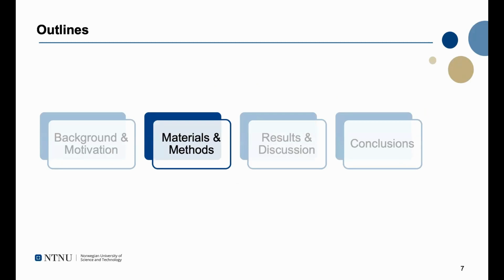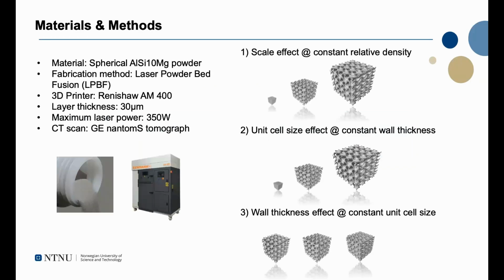So let's jump to the materials and methods. All the specimens are fabricated from aluminum silicon magnesium powder with laser powder bed fusion. The layer thickness is 30 microns, the maximum power is 350 watts, and CT scans were used. For all the geometries, the specimens were classified into 3 categories.